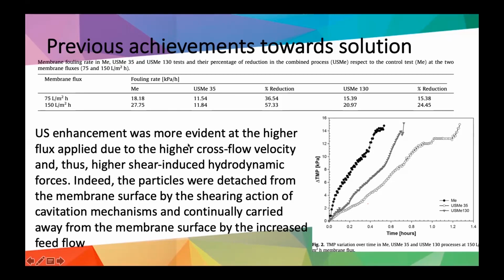This was due to the higher cross-flow velocity and the higher shear-induced hydrodynamic forces, where the particles were detached from the membrane surface by the shearing action and the cavitation mechanism, which carries them away from the membrane surface, increasing the feed flow and the flow through the membranes by the action of this ultrasound.